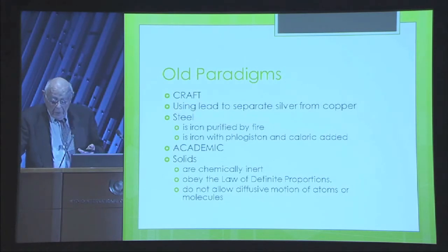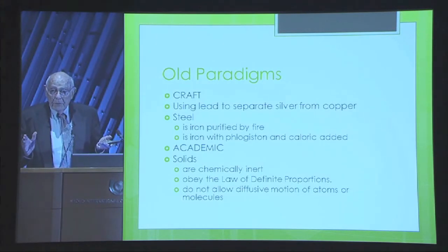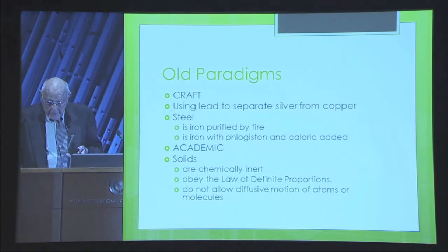So, but it took another 20 years for the ceramics and the ionics people to realize that the motion in the solid state was caused by the vacant sites in the crystal structure. It's the vacancy that is moving, and it took another 30 years for metallurgists to realize this. So the time scale in the field of material science until I came was very, very slow. And this left many things to be done.